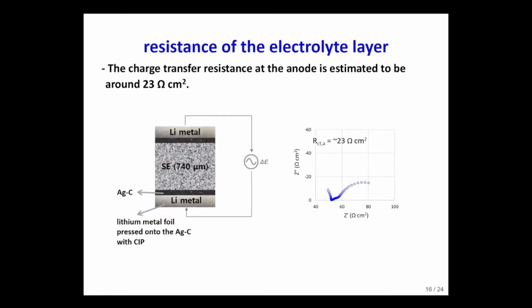The next one was the charge transfer resistance at the anode. We designed a special symmetric cell for this measurement. Silver carbon layers were coated on both sides of the electrolyte pellet, and it was pressed with a warm isostatic press. Then lithium metal foils were laminated on both sides of it and pressed with a cold isostatic press. During this process, the lithiation of the silver carbon layer happened.